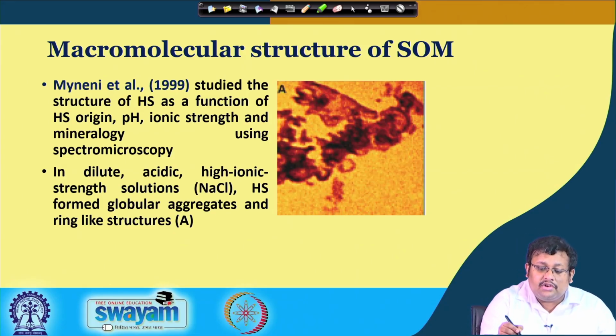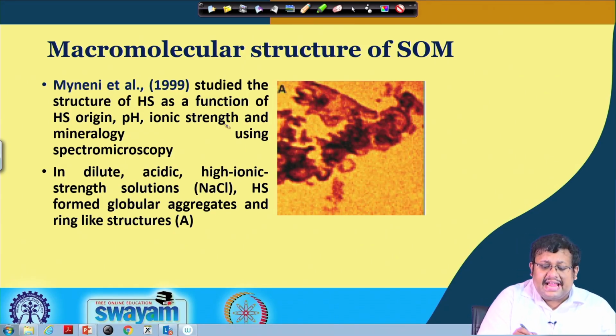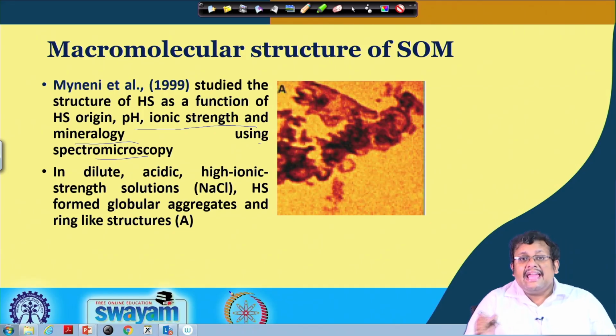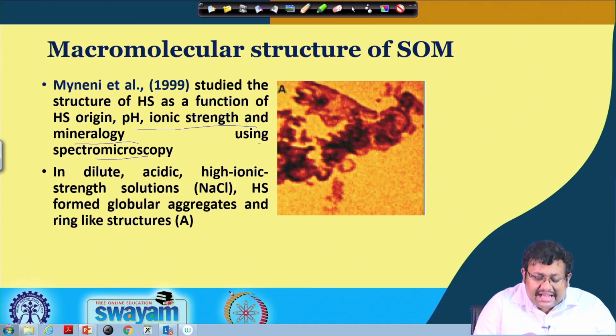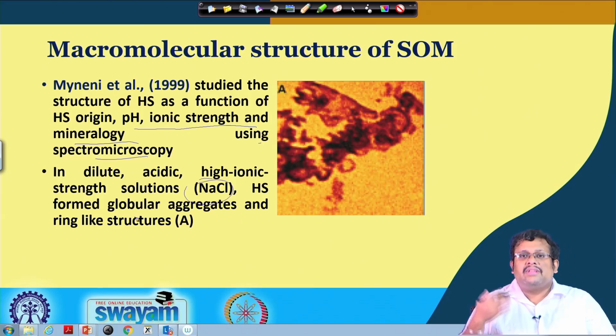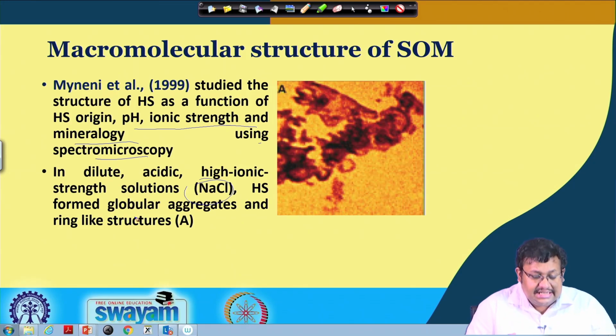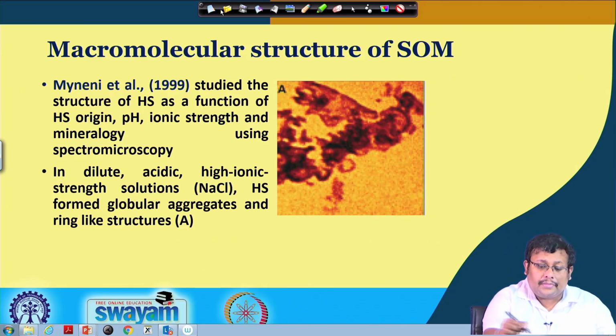They studied the structure of humus as a function of humus origin, pH, ionic strength and mineralogy using spectromicroscopy, and they have also given different structural patterns. In dilute acidic, high ionic strength conditions, like sodium chloride at high concentration of the electrolyte, humus formed globular aggregates and ring-like structures, as you can see here.